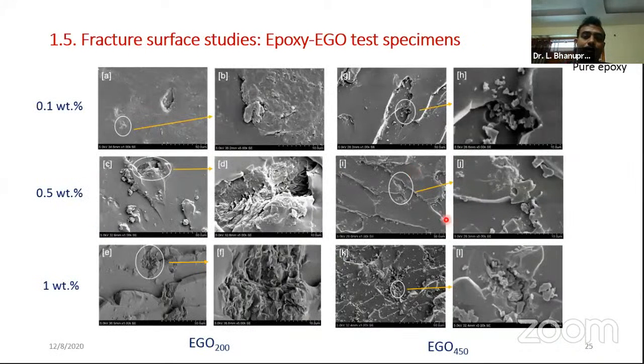And we have seen the fracture surface images, and we could notice that at one weight percentage of nanofiller combination, we can see a very high amount of agglomerations. When it is at low concentration, you can see very nice homogeneous dispersions being observed. When it is one weight percentage, this kind of clumsy clusters of agglomerated nanofillers are observed. So in further experiments, we have not used 1 weight percentage. We have restricted our experiments to less than 0.5 weight percentage.